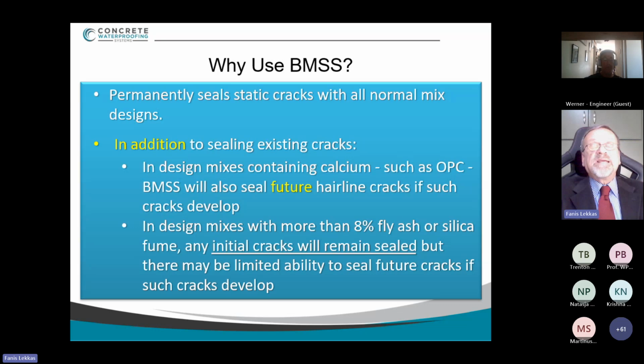And then, as long as there is free calcium in the concrete, in case the concrete develops a future static crack, you know, sometimes we have such high temperatures around our world nowadays that concrete even 5 or 6 or 7 years old has been known to present shrinkage cracks, because of expansion and contraction under the very high thermal stresses. So if there is free calcium in future, then this technology will even seal a future static crack. Now, in case we really want our project to enjoy future crack sealing, we generally try to avoid pozzolanic materials like silica fume, microsilica, or fly ash in high percentages, because they tend to block the free calcium. So we can limit these pozzolanic materials to around 8%, because generally we use them to make the concrete more dense and waterproof, right?